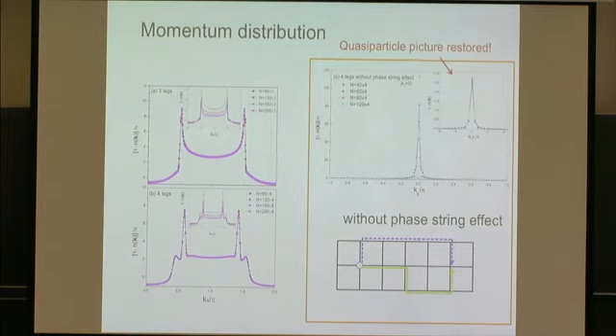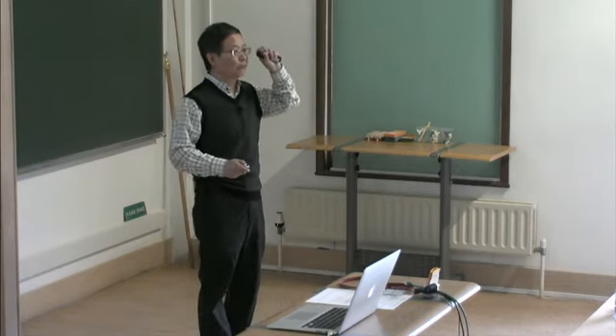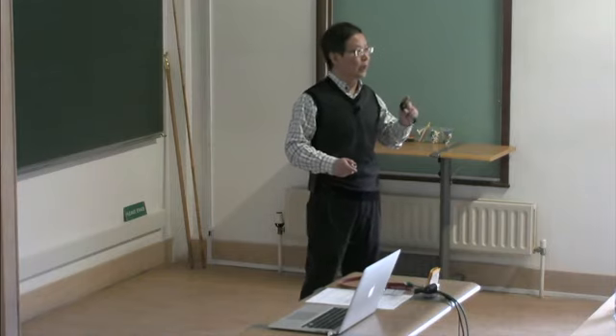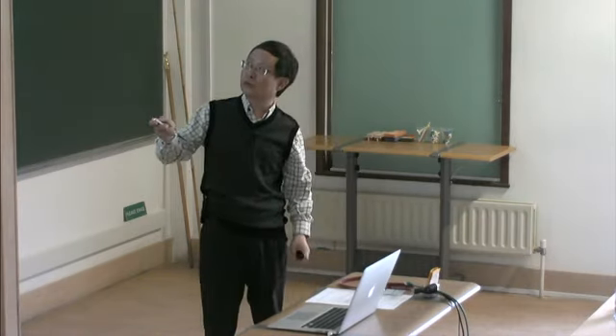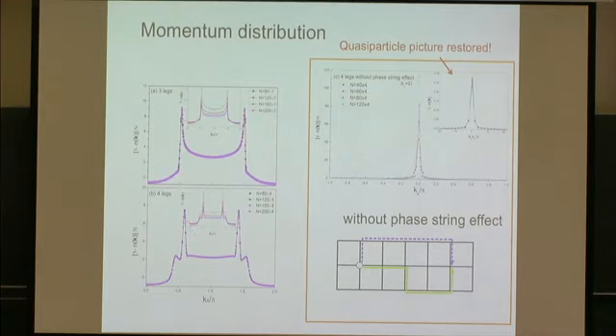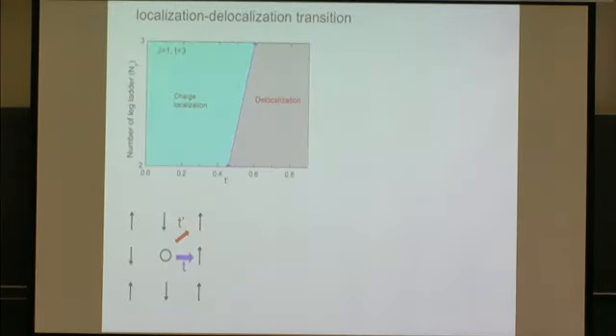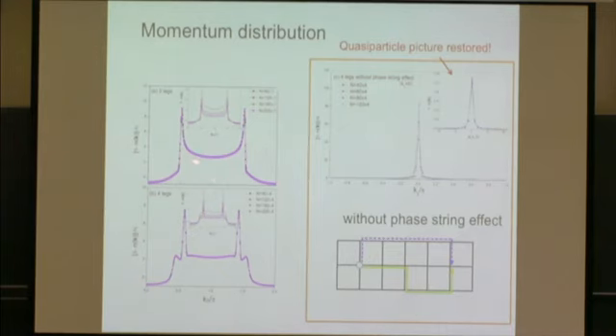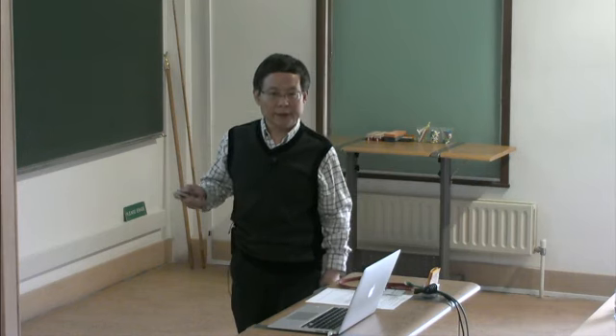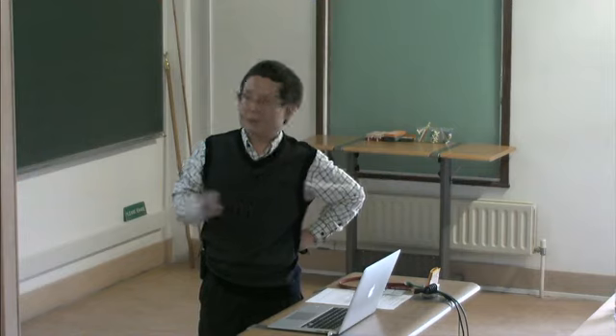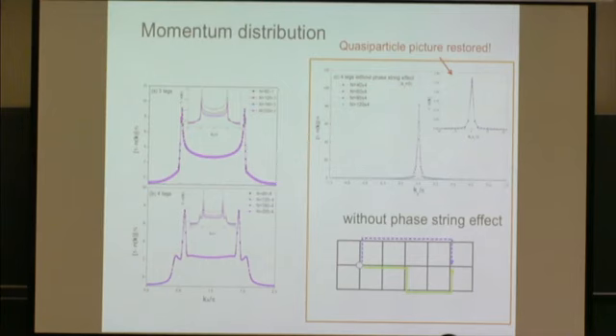There is a scaling law: notice that n_k is multiplied by n, so this height is actually proportional to 1 over n. In other words, if there is a quasi-particle weight, it goes to 0. This scaling behavior for 2-, 3-, 4-leg really tells you this is a localized profile. This is the electron distribution function, the electron operator n_k. You subtract the half filling. Half filling is flat; there's no Fermi surface. What is the density of electrons? Just one hole. This is the sum rule. This is the momentum distribution; sum up all of them, it gives you one. We just put in one hole.